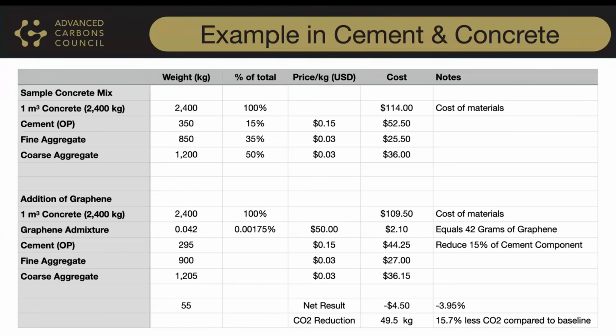The net result is that we are going to reduce the actual cost of goods bill for this cubic meter of concrete by $4.50, which is a 4% savings in cost of goods. Plus, the big news is that at $50 per kilo of the graphene, we save the 4%, but we're also reducing by almost 16% the carbon footprint.